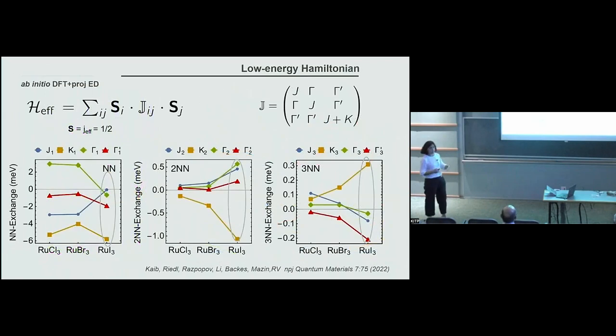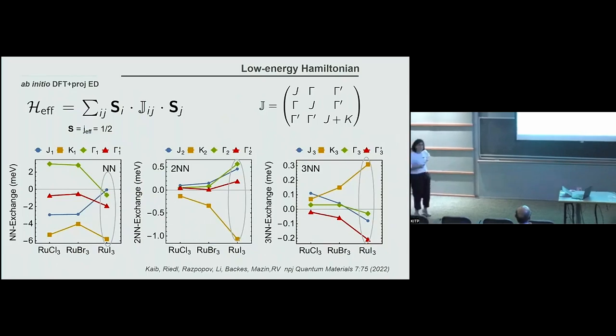So now for these three materials, we extract the spin exchange interactions. And what is very interesting, and let me concentrate on the ruthenium iodine, is that it's not only important that you have, let me concentrate, for instance, on the Kitaev-Heisenberg, the first neighbors, second neighbors, as well as third neighbors, but the third neighbor Kitaev interaction is antiferromagnetic. So it's ferromagnetic, ferromagnetic, antiferromagnetic. And then there is also an important gamma-3 term here, which is ferromagnetic.